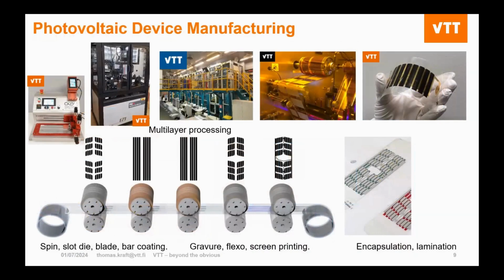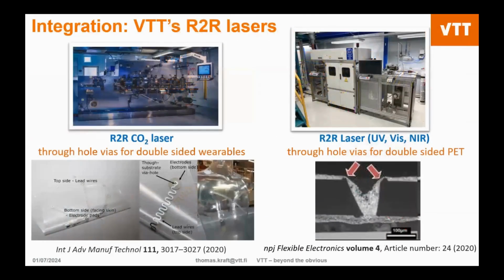Now my background is with photovoltaic manufacturing. So what we do here is we're printing multiple layered devices. Often we'll have the conductive transparent oxide, and then an electron transport layer and an active layer, then maybe a hole transport layer, followed by your back contact electrode. And for integration, this is where we get more into the depth of the case study that I want to discuss today, where we have different laser options to access the devices after post process, if they've been encapsulated, or in this case you can use a CO2 laser. Here are two examples from work that we published relatively recently.